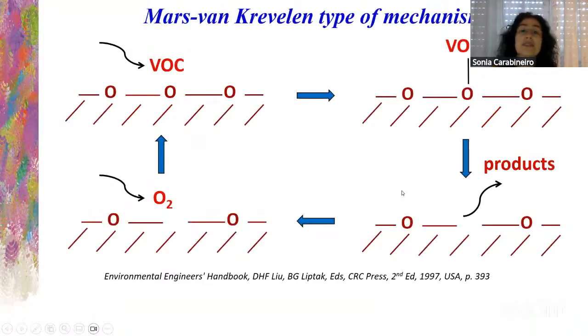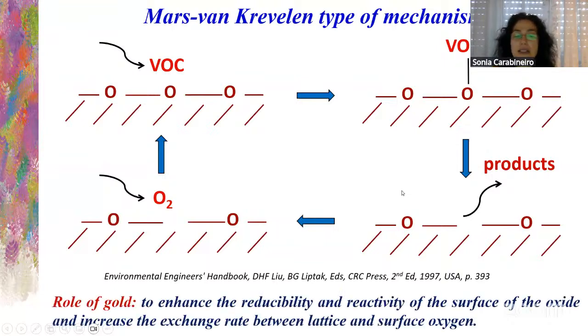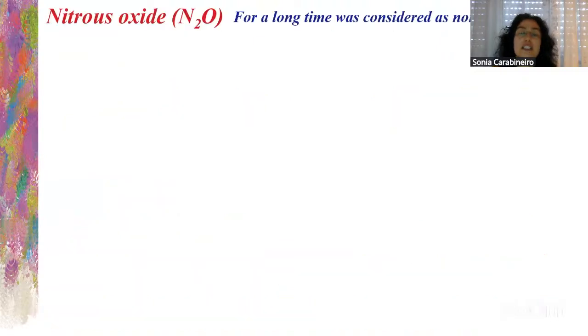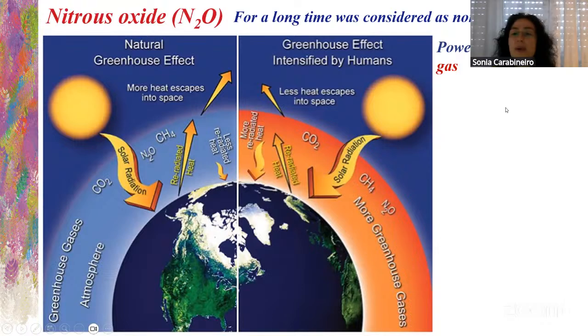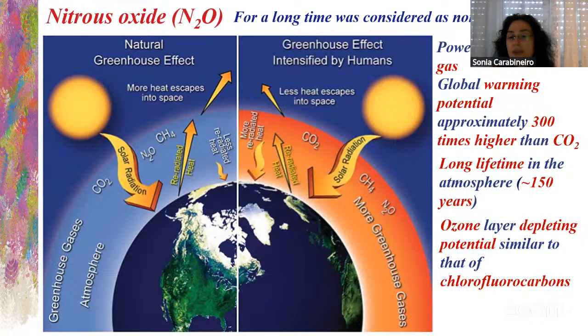So we propose a Mars van Krevelen type of mechanism, okay, in which the role of gold is to enhance the reducibility and reactivity of the surface and increase the exchange rate between lattice and surface oxygen. Also, we did this test for nitrous oxide, which is N2O, that for a long time was considered a non-pollutant species, but in fact, it is a greenhouse gas, okay? And it has a global warming potential 300 times higher than CO2, and a long lifetime in the atmosphere. The ozone layer depletion potential is similar to that of CFCs, and it has been increasing, and so on.